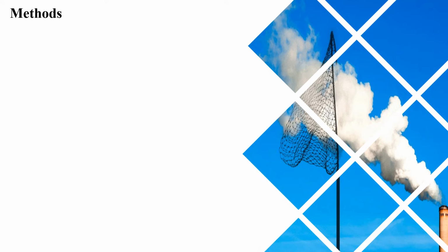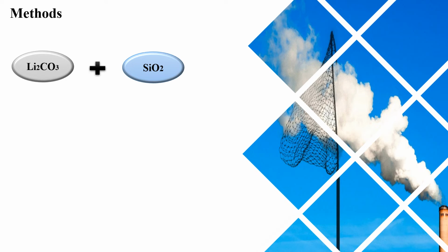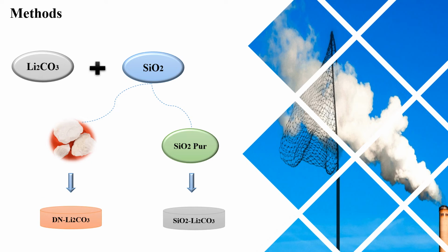Let's move on to methods. In our work, lithium silicate sorbents are obtained by mixing lithium carbonate, Li2CO3, as lithium precursor, with silica, SiO2. This latter comes from two sources. The first is derived from Algerian diatomite, DN, which comes from Algeria. The second is the pure SiO2, which comes from Aldrich. The two elaborated materials were named DN-Li2CO3 and SiO2-Li2CO3, respectively, according to the used source of SiO2.